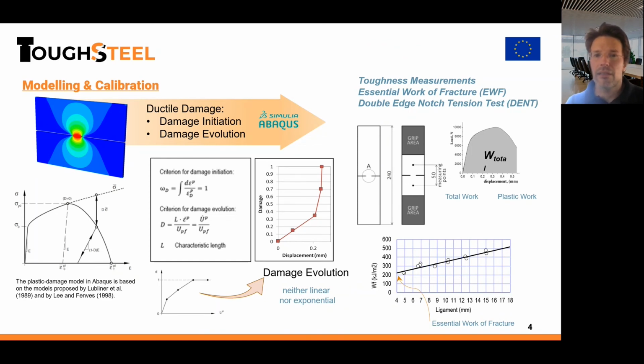The damage initiation is the equivalent plastic strain as a function of the triaxiality when the element starts to lose stiffness. And the damage evolution defines how the damage grows as a function of the element plastic displacement, not the plastic strain. This is an important thing. We use the plastic displacement in the element to avoid problems with the element size in the mesh. Normally, linear or exponential laws are used, but now we propose to use a power law that grows fast in the last part of the plastic displacement.